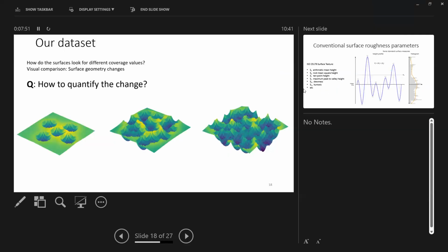So one of the problems for shot peening is that you can't really control so much the coverage percentage, which is how much of the surface has been impacted. Oftentimes you're shooting small balls, and oftentimes they just think, okay, we keep on shooting until a certain time, and then we roughly say coverage percentage is something like that. But for experiments, you want to have a better handle on whether coverage percentage influences your specific findings.